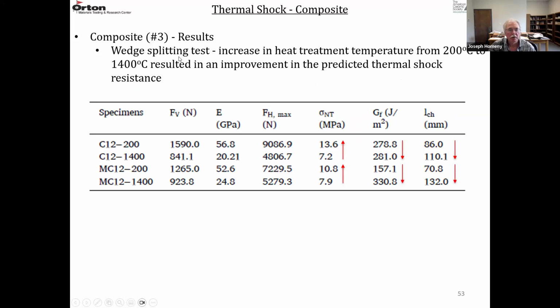So these are the results from the wedge splitting test. The increase in heat treatment temperature from 200 to 1400 resulted in an improvement in the predicted thermal shock behavior. So C12 at 200 and 1400 curing, MC12 at 200 and 1400 curing. This is your vertical force in newtons. This is your Young's elastic modulus in GPa. This is the horizontal force maximum in newtons. So the calculated tensile strength in megapascals, calculated fracture surface energy in joules per meter squared, and then your characteristic length in millimeters.